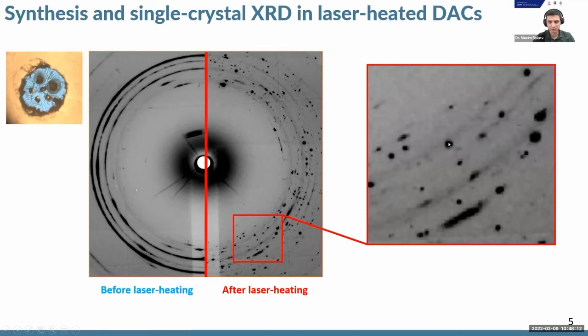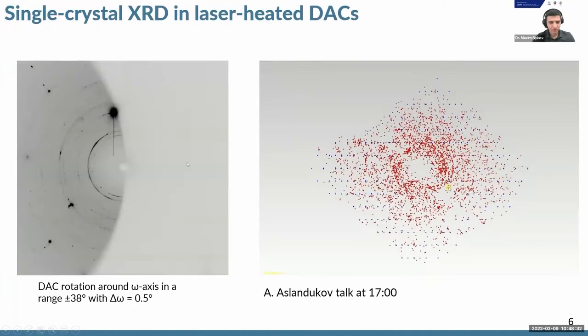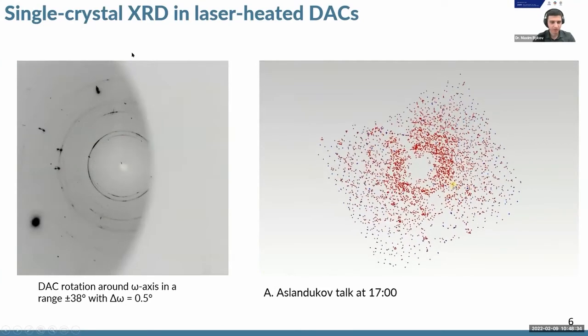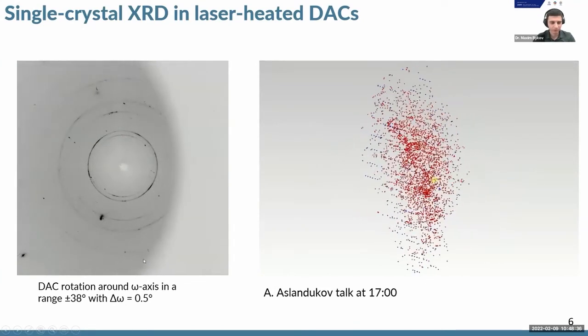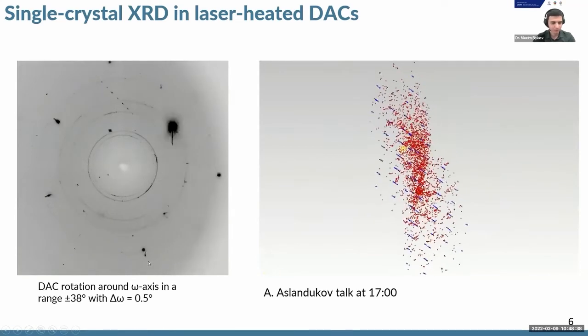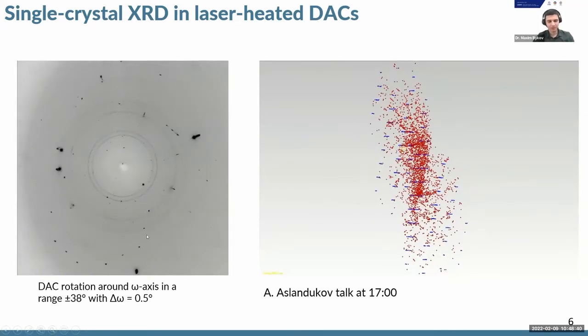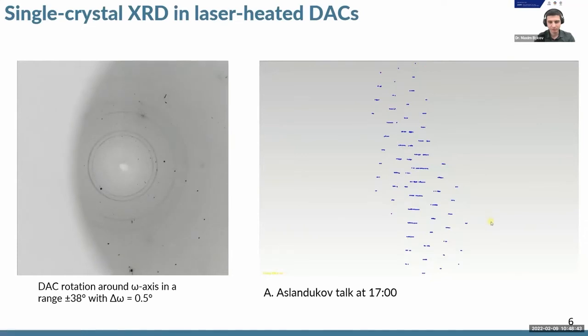If you find a way to understand which grain these nice sharp spots belong to, you can determine the rotation matrix and then use very well-known approaches of single crystal X-ray diffraction to solve and refine the structure without prior knowledge about its structure type, composition, and possible candidate structures. In a typical experiment, we would rotate a diamond anvil cell around one of the goniometer axes in a range of plus minus 38 degrees and collect a diffraction pattern every 0.5 degrees.